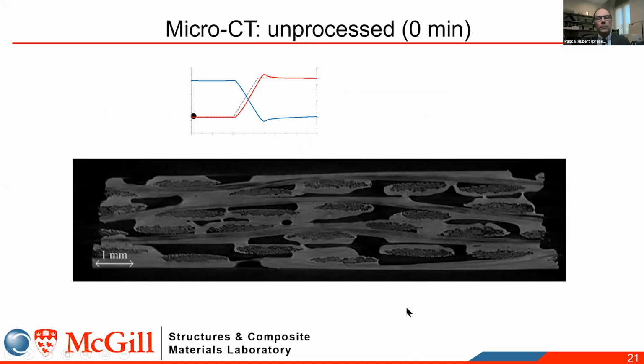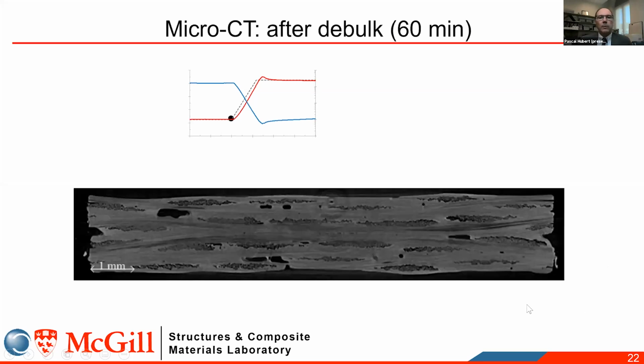So if we look at the material in its initial state, you see a very porous material. It has been engineered for that so that we can evacuate all the air. And we see the fiber toes that are not impregnated and the resin film in light gray that is surrounding the material. Now we see that after we apply vacuum for some time, we get rid of some of those macrovoids through the consolidation by the vacuum pressure.